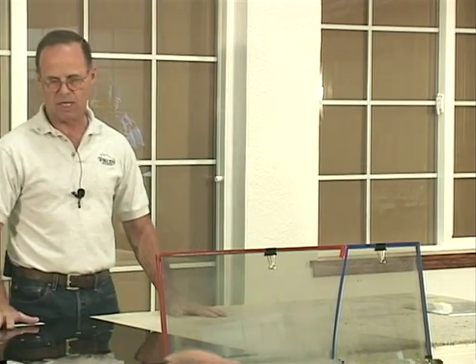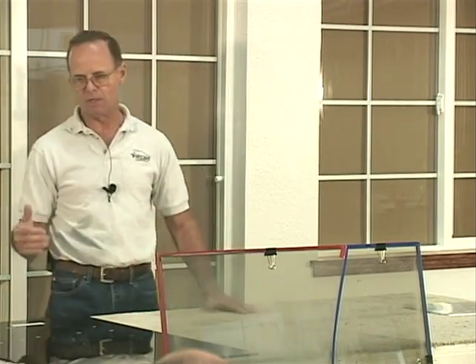The other way glass corrosion happens is with glass manufacturers. When they're storing glass, they'll take sheets of glass and just stack sheet after sheet after sheet after sheet. If there's any moisture between them sheets, the exact same thing will happen. The pH in that moisture will build up and will rise. And when the pH gets high enough, it will actually corrode the glass. So it's the pH that's actually doing the corroding, not anything else. It has nothing to do with anything else that's happening. And the hydrofluoric acid will not show up on corrosion. It has nothing to do with corrosion. But I just wanted to point that out.